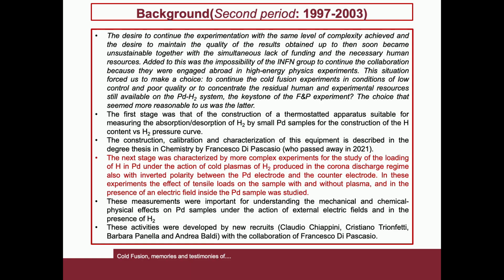The next stage was characterized by more complex experiments for the study of hydrogen loading in palladium under the action of a cold hydrogen plasma produced in corona discharge regime, even with reversed polarity between the palladium electrode and the counter electrode. In this experiment, the effect of tensile loads on the sample with and without plasma and the presence of an internal electric field in the palladium sample was studied.